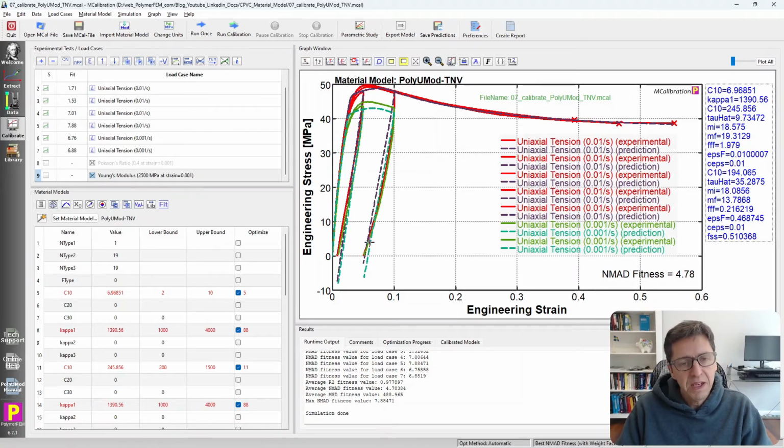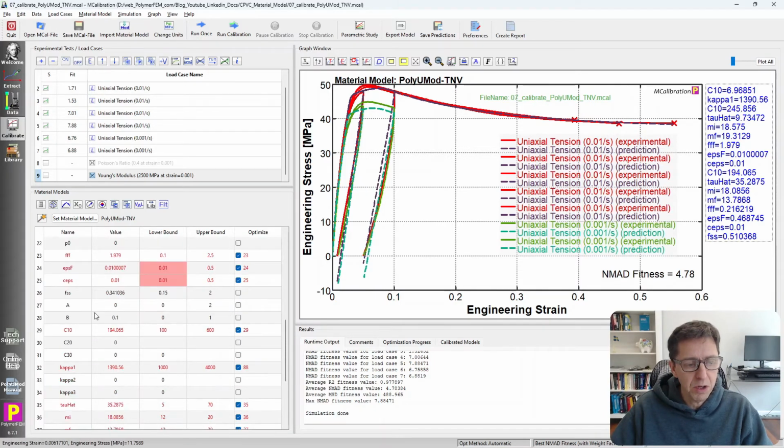That is, the modulus is reduced during unloading due to the introduction of plastic strain, and that's captured by some of the parameters in the model, particularly the CEPS parameter, for example. So there are things in here that allow us to get this prediction that were designed for this particular purpose, and that's why this works better than the other models.